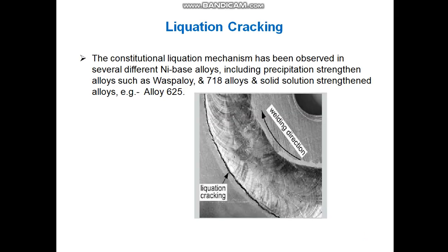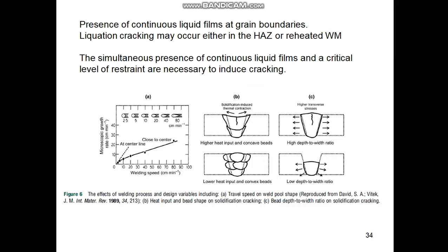This is another example of liquation cracking, most of the time found in precipitation strengthened alloys, Waspaloy and 718 alloys, and solution strengthened alloys like alloy 625. Liquefaction cracking is a constitutional liquation phenomenon. You would see a crack in the heat affected zone side. Now this is a capture from one research article I have cited in the reference.